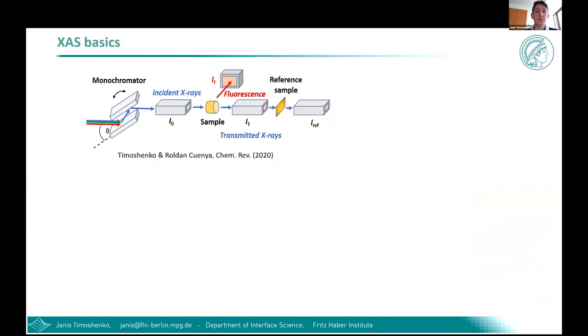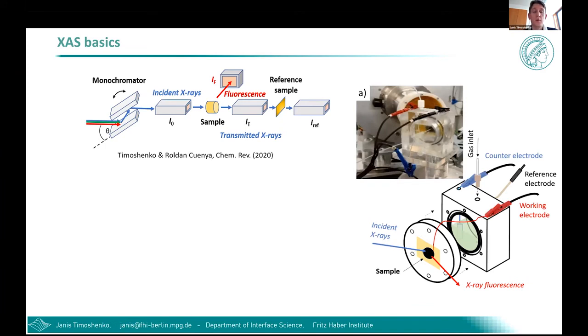So in X-ray absorption spectroscopy, we are measuring absorption coefficient for X-rays as a function of the energy of incident X-ray photons. And these experiments can be performed directly by just measuring attenuation of X-rays inside your sample, or indirectly by measuring the intensity of fluorescence, which is proportional to the absorption coefficient. And clearly, in the context of operando studies, an important benefit of X-ray absorption spectroscopy is the high penetration depth of X-rays, which means we can not just study our samples in air, but also in quite complex environments, such as electrochemical cells. And one approach could be that we can deposit our catalyst on carbon electrode, and then this carbon electrode is used also as a window, both for incoming incident X-rays, as well as for X-ray fluorescent radiation.